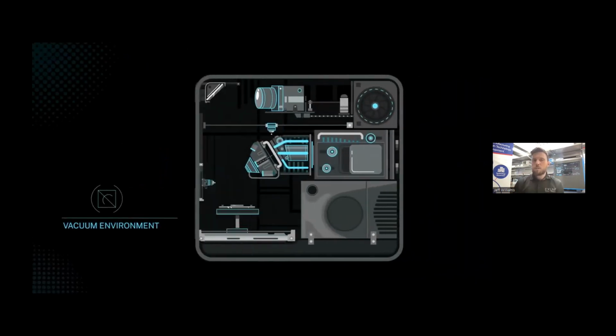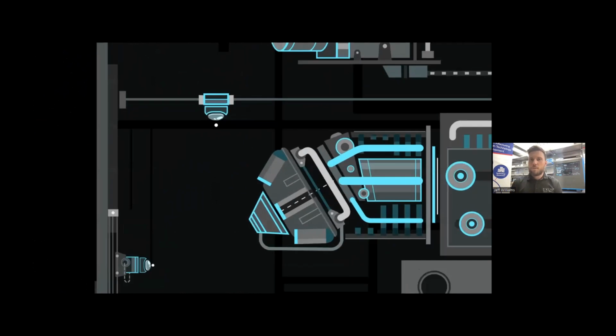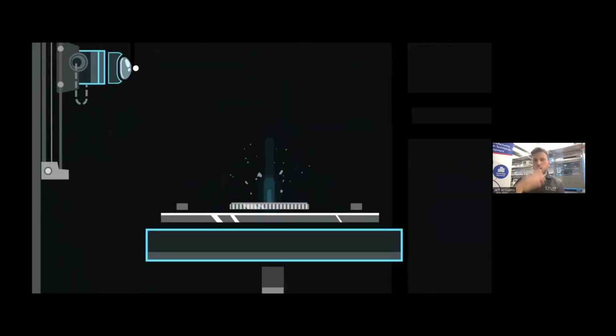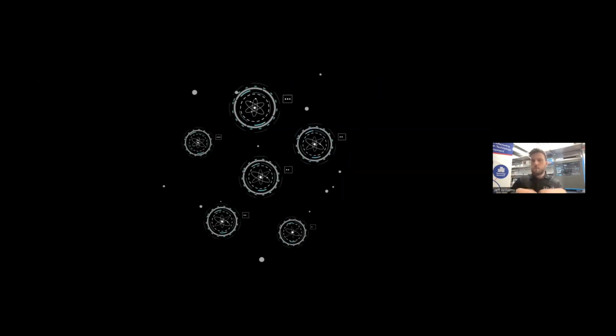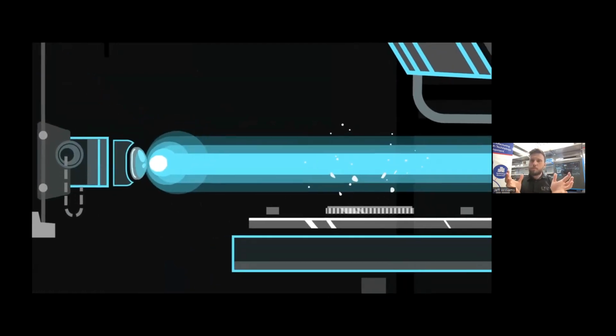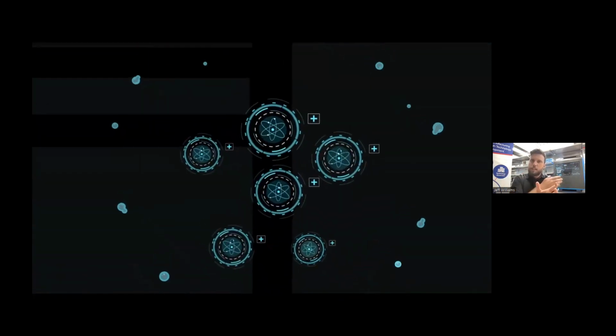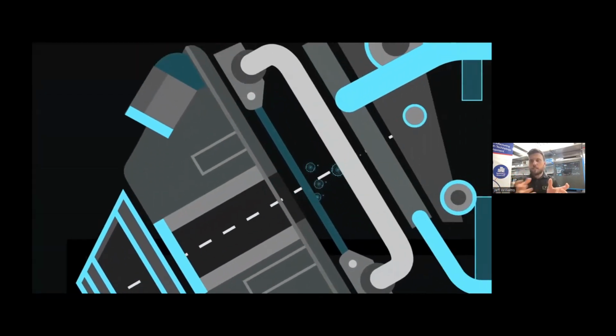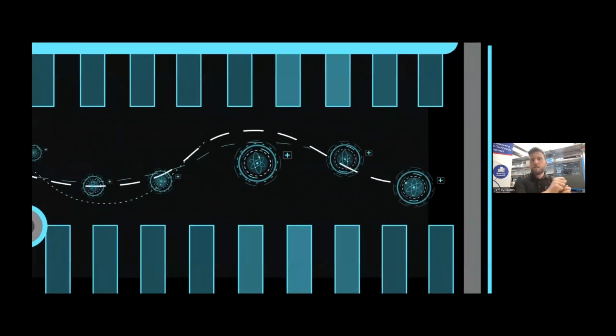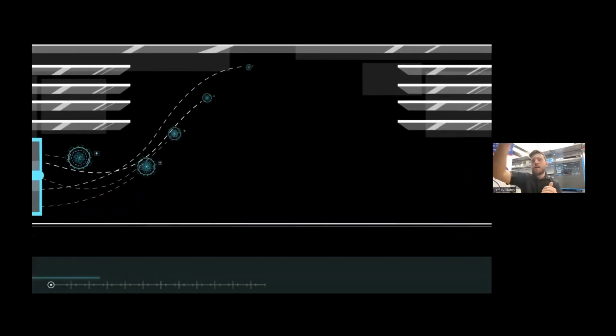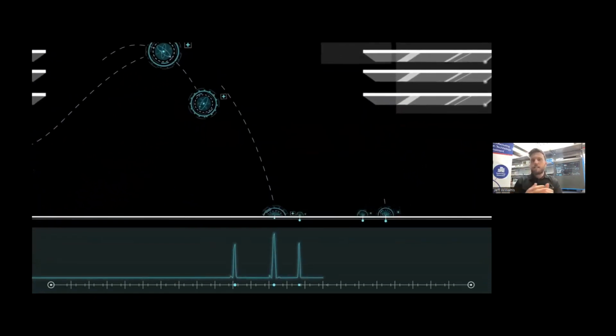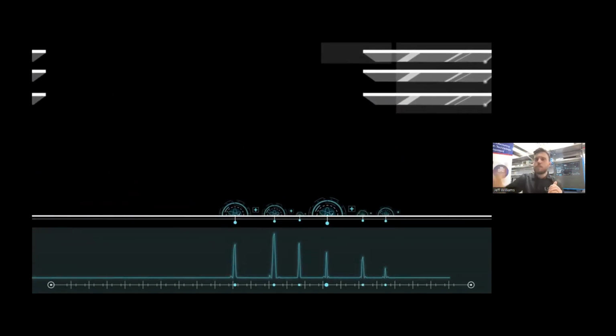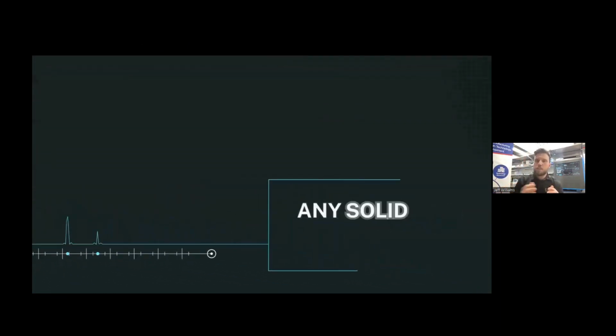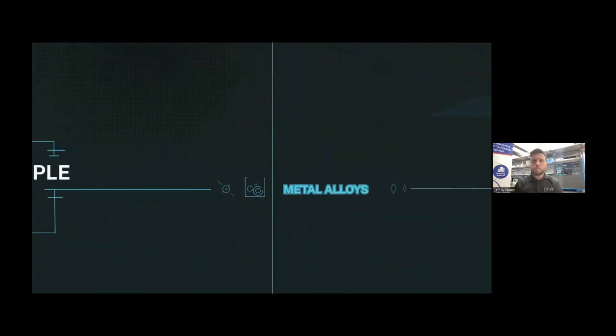The door then closes and we go under a high vacuum environment. One laser is going to come down and hit the sample and create a neutral particle cloud. And the second laser is going to come in and create our ions. This is what we're actually going to be analyzing through what's called time of flight mass spectrometry. We basically kick the ions really hard and they fly as a function of mass. So hydrogen goes very fast, uranium goes very slow, and we end up with time series data.